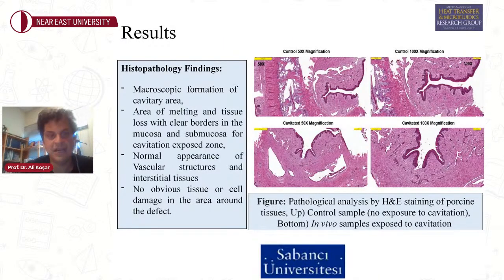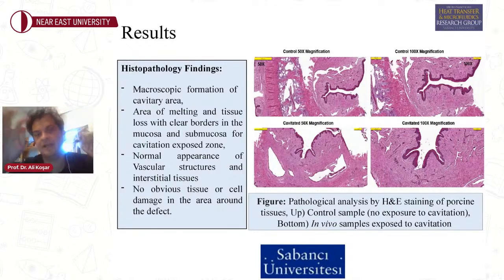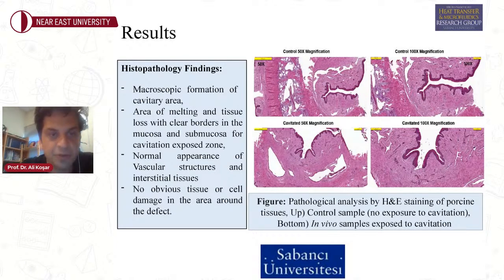And here you can see histopathology results of the pathological analysis. Here we have H&E staining of the porcine tissues, and we compare it to the control sample where we do not have cavitating flows. And we have seen that in exposed areas, we can really remove material. We have erosion. However, there was no obvious damage in the area around the defect. So we were happy about the local characteristics of our approach.